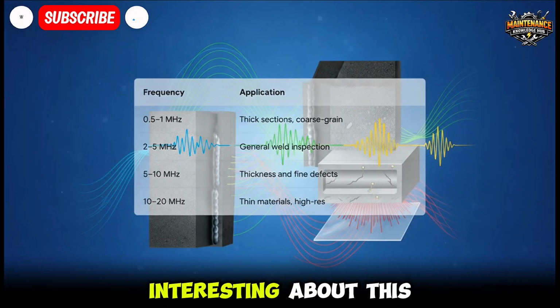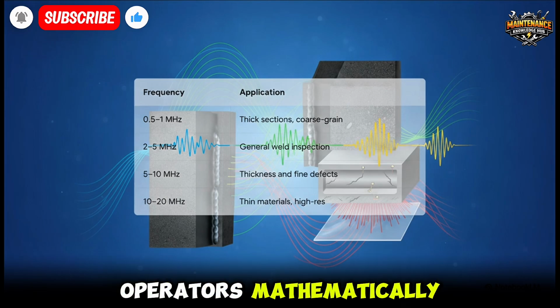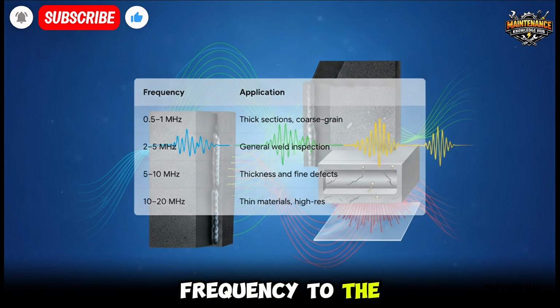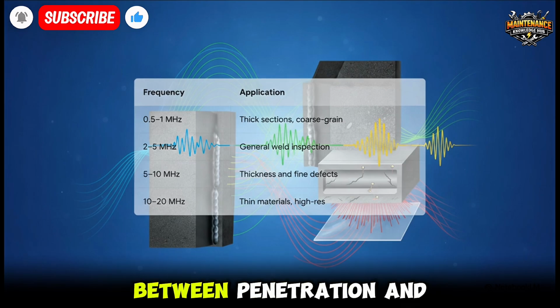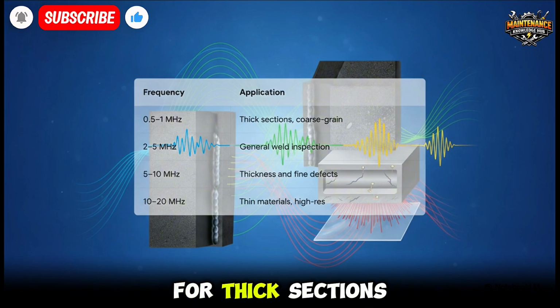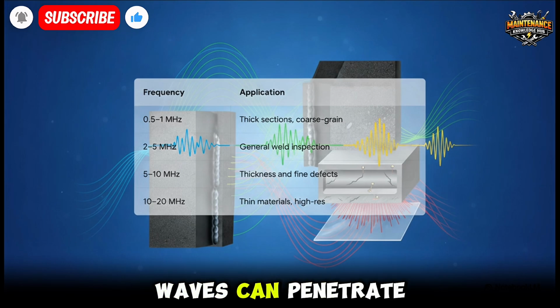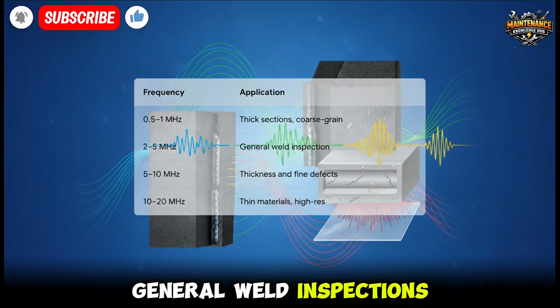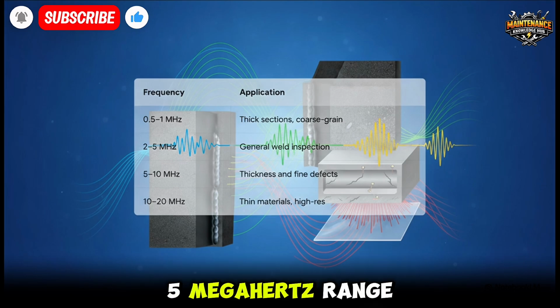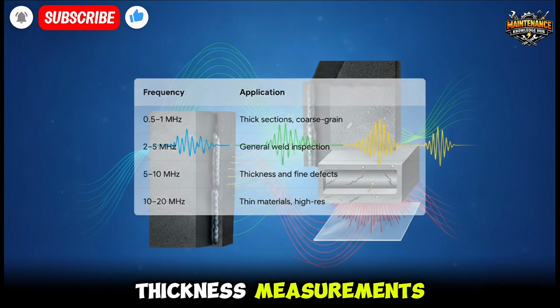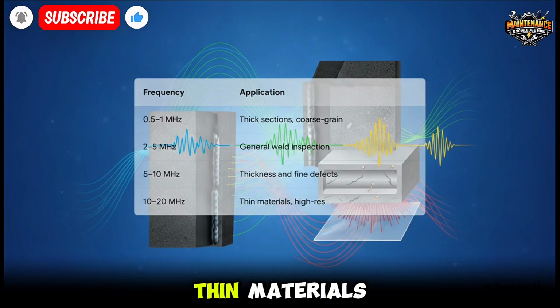Now, what's really interesting about this slide is seeing how operators mathematically match the sound frequency to the specific job at hand. It is entirely a balancing act between penetration and resolution. For thick sections or coarse-grained materials, you have to drop the frequency down to 0.5 to 1 megahertz, so those longer waves can penetrate deep. General weld inspections sit comfortably in the 2 to 5 megahertz range. But for precise thickness measurements or finding tiny microflaws in thin materials, you need high resolution, maxing out the frequency between 10 and 20 megahertz.